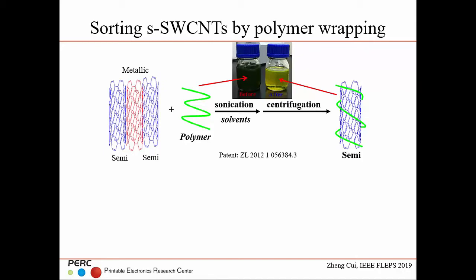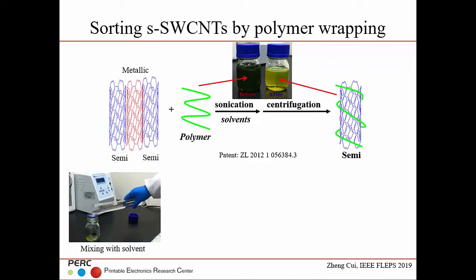They can selectively wrap up, or recognize, the semiconductor tube, only wrapping the semiconductor tube. And then you have the mixture of the ink. Then you use centrifugation to get rid of the metallic tube, because the metallic is not wrapped up and cannot dissolve in solvent. Then you end up with the semiconducting carbon ink. So that's the way we do it.